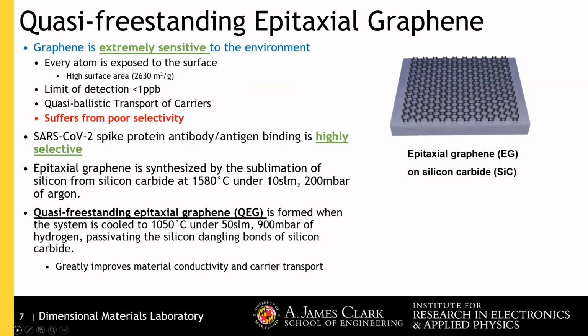So what is quasi-freestanding epitaxial graphene? I'll call it QEG for short. Well, first off, quasi-epitaxial bilayer graphene. Graphene by itself is an epitaxial structure. That's that honeycomb lattice that you hear. But usually it's only one layer, and it's just one layer of carbon atoms. With bilayer graphene, we have 2 layers of carbon kind of smushed together, very close to each other, and then it's supported by the silicon carbide structure. That's where the quasi-freestanding part comes from.